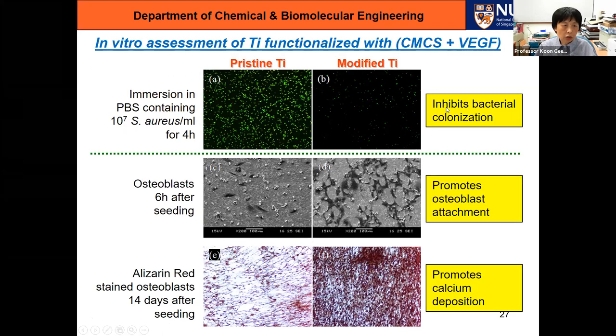The first row here shows the effect on bacterial colonization. This is titanium after 4 hours exposed to bacteria. The green dots are colonies of bacteria. So for titanium, not only do osteoblasts adhere well, unfortunately, bacteria also adhere well. But after modification with our coating, the CMCS plus VEGF, you can see that the number of bacterial colonies has greatly reduced. And then we look at what happens to the osteoblast. This is the titanium surface after 6 hours. We see some spreading and attachment of the osteoblast. But compared to the modified titanium, the extent of attachment and spreading is much more on the modified titanium.